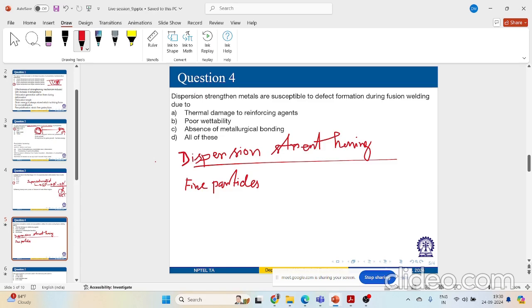Now, this question asks: dispersion strengthened metals are susceptible to defect formation during fusion welding due to, is it, thermal damage to reinforcing agents? If you are doing fusion welding, you are going beyond the melting temperature. Possibly you are not going to the melting temperature of these particles. These particles always have a much higher melting temperature compared to the base metal, right? If you are mixing Al2O3 or SiC with aluminium, aluminium has a melting temperature around 660. What is the SiC melting temperature? It is above 1000. So it may happen you are not going beyond the melting temperature of those particles, but because of the increase in temperature, you will be thermally damaging those reinforcing agents.